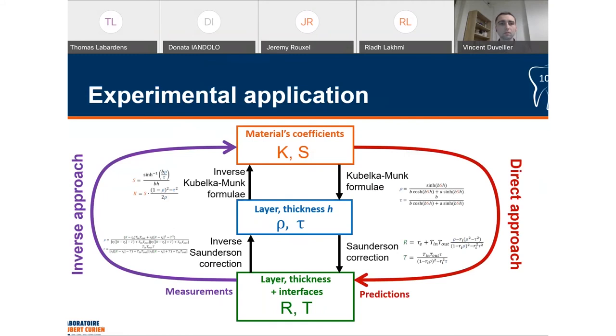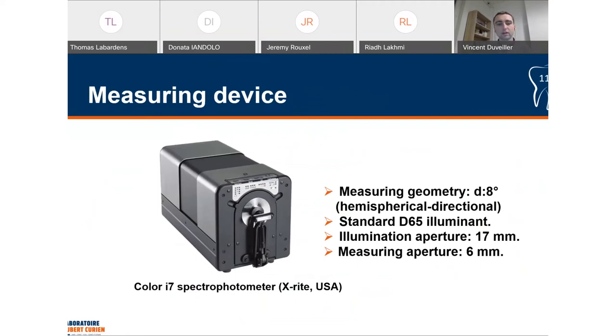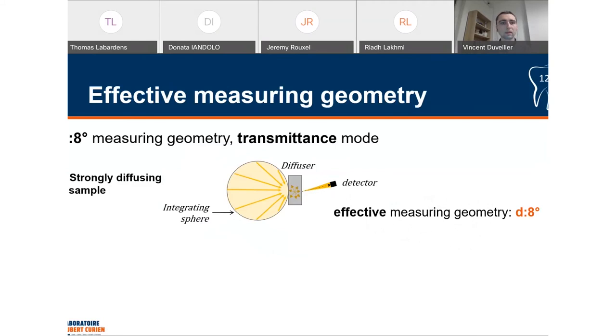transmittance factors. These transmittance and reflectance factors were measured using the Color i7 spectrophotometer from X-Rite. The measuring geometry of this device is hemispherical directional. The illuminant is the standard D65. To measure the transmittance and reflectance of our dental materials, as we know that they are highly translucent, we used the largest illumination aperture possible of 17 millimeters and the smallest measuring aperture possible of 6 millimeters to avoid the edge loss phenomenon, which is known to occur during the measurements of highly translucent materials. So now let's have a look at the effective measuring geometry.